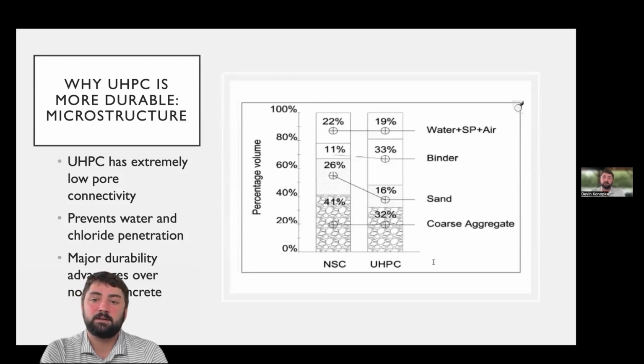This slide highlights why UHPC performs the way it does. The key difference is the microstructure. UHPC is designed with an extremely dense particle packing and a very low water to cementitious ratio. That creates a microstructure with very low pore connectivity, which is what prevents water, chlorides, and other harmful agents from moving through the material. Normal concrete has a network of connected capillary pores, while UHPC almost entirely eliminates that, which makes this the foundation for all the durability advantages that we just talked about.